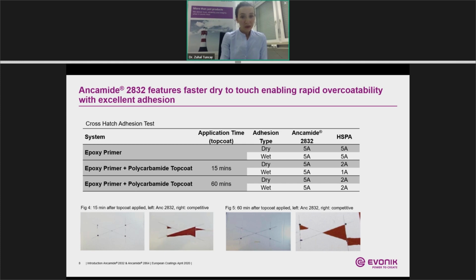So 2832 allows rapid overcoatability with excellent adhesion. To demonstrate these attributes, we conducted a crosshatch adhesion test. In this table, we have 3 different test protocols. The first is epoxy primer applied on steel and allowed to cure for 24 hours, and both wet and dry crosshatch adhesion are measured. In this case, 2832 and also the competitive system, which was a high solid polyamide, provide excellent adhesion.